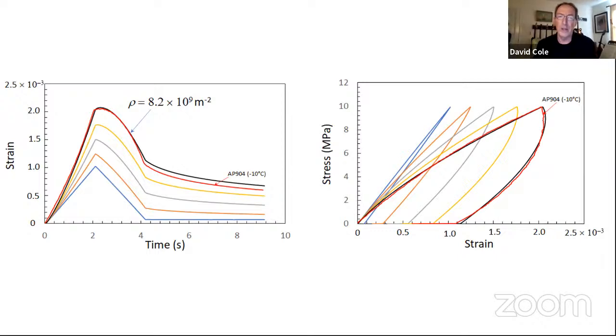So once I ran these calculations, I've got to say, I was shocked, pleasantly shocked, but still very shocked, that this regime with fast loading, which is quite different from the conditions for which the model was developed, still handles this result to a certain point. I'm not to the point where I can predict yet what the dislocation density is under certain loading conditions, but I know that once I develop that relationship, I can actually handle these results and model it pretty effectively.